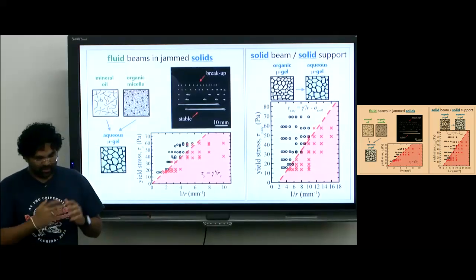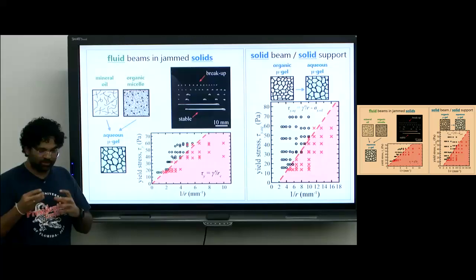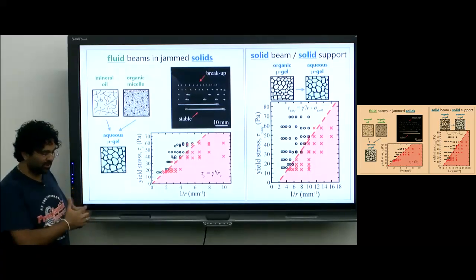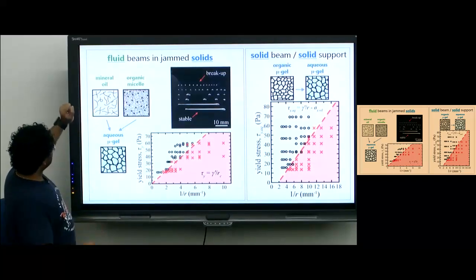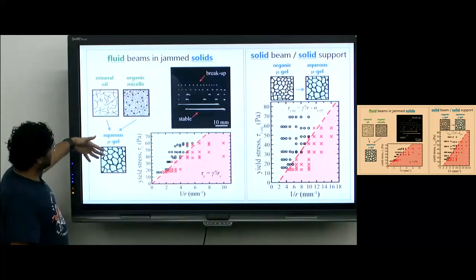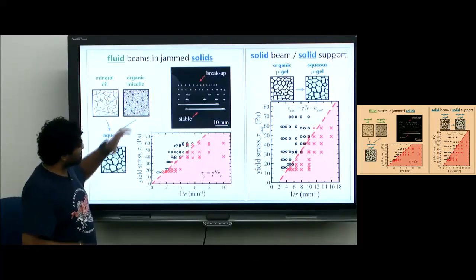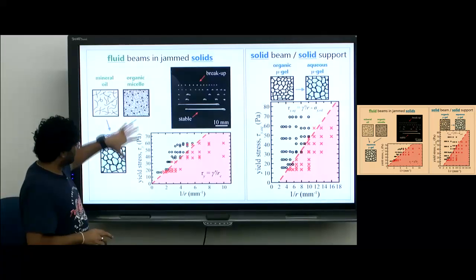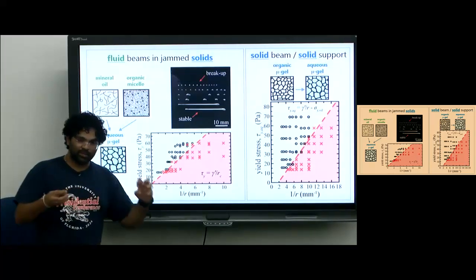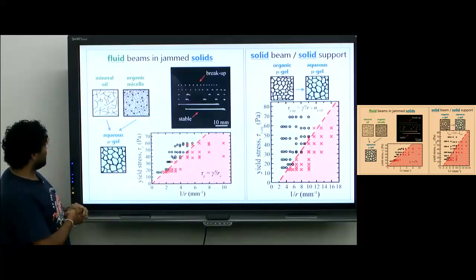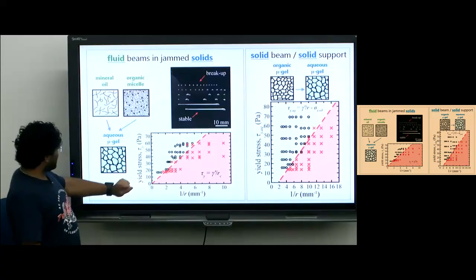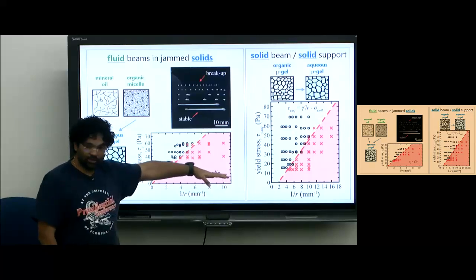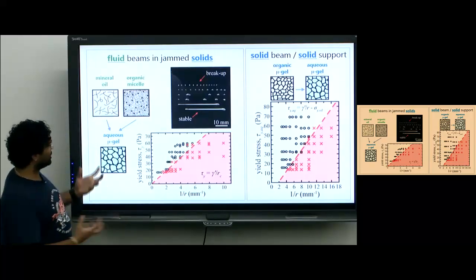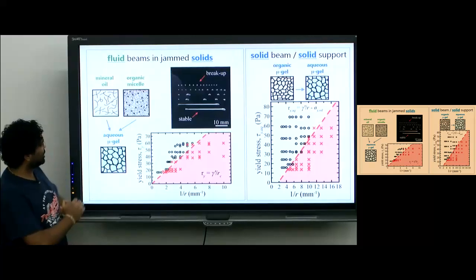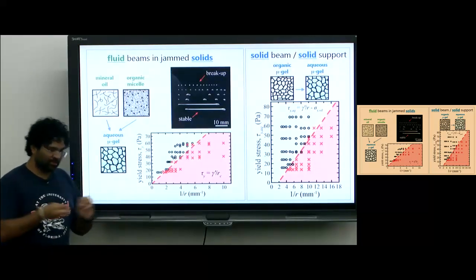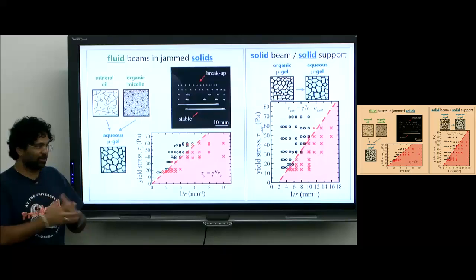Like I was saying earlier, these are examples of different types of inks printed into different types of support material. Here, for example, it's either mineral oil or organic micelle printed into an aqueous solution. There are considerations where you need to look at what regime of yield stress and what regime of diameters you can print to get a stable structure. For example, if it's a really large diameter and really low yield stress, you're going to break up the printed material. This was mapped out in the work that I talked about earlier, and you can figure out what diameters you can print without breaking up your printed structure.